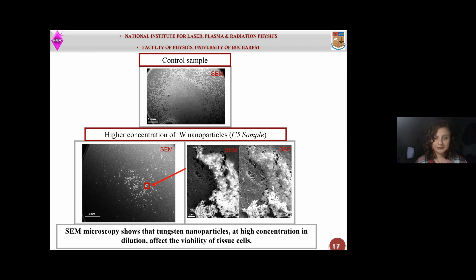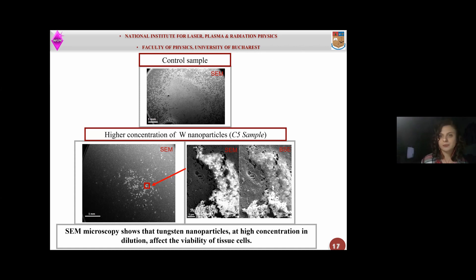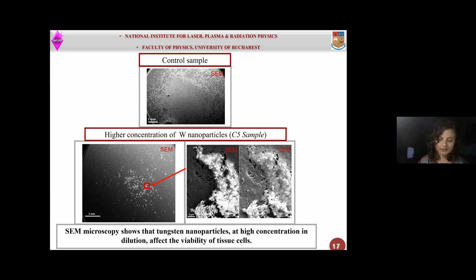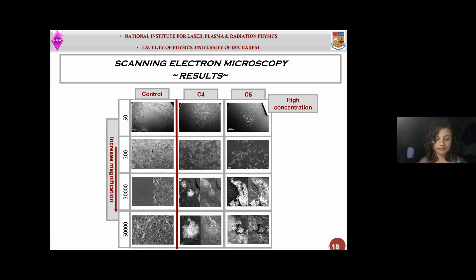In the next slide, you can observe how nanoparticles interact with cells at higher concentrations in contrast with the control sample. You can observe that cells are not like the control sample ones — attached on the surface and interconnected. In contrast, they remain singular, and the nanoparticles cover the cells and penetrate the membrane. Moreover, at different magnifications, nanoparticles are observed both on and inside the cell.